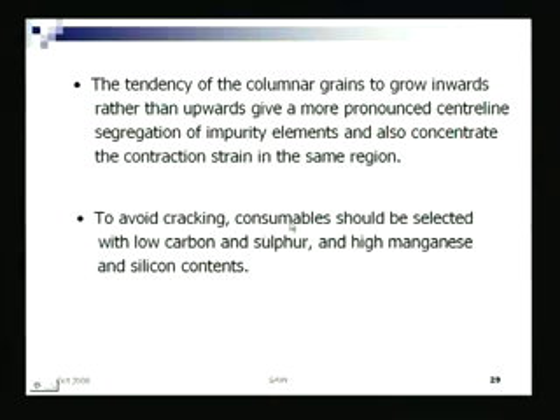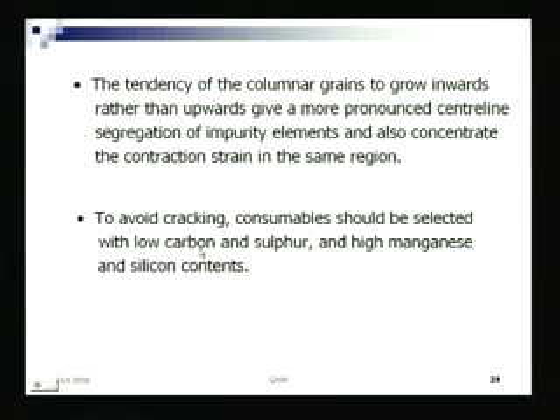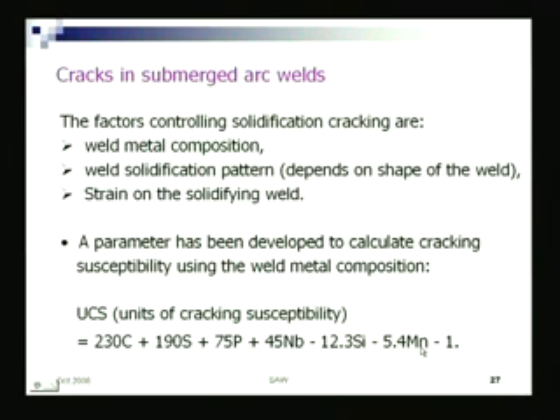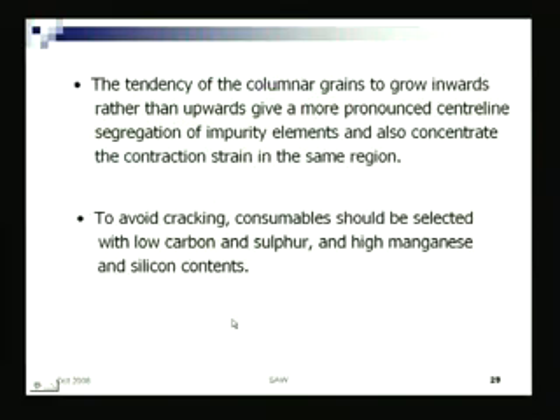So welding consumable has to be so chosen, that is what is mentioned. If it is submerged arc welding, your electrode as well as the flux should be so chosen that it has low carbon and sulfur, and high manganese and silicon contents, because here they are the negative terms. So if I have higher silicon and manganese, it is better for me, it reduces the UCS, that units of cracking susceptibility parameter reduces.